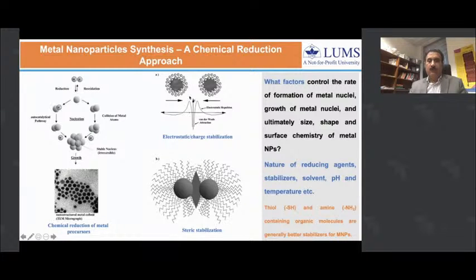The two ways we stabilize them is, one is electrostatic stabilization, in which we coat these nanoparticles with some charged molecules like sodium citrate or sodium acrylate, so that all particles have similar charge, positive or negative, and due to similar charges these particles repel each other.